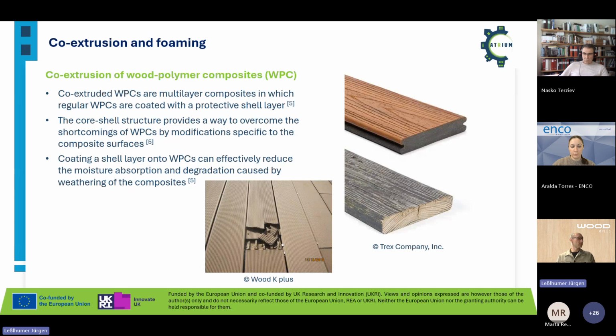And the co-extrusion of these wood polymer composites gives multi-layer composites in which regular WPCs are coated with a protective shell layer, as you can see here in the right picture. It can be on only one half of the profile, or this co-extruded layer can be around the whole core. And this structure provides a way to overcome the shortcomings of this WPC. And coating a shell layer onto this WPC can effectively reduce the moisture absorption and degradation caused by weathering of the composites, and avoid things like this, which you can see in the picture in the middle.